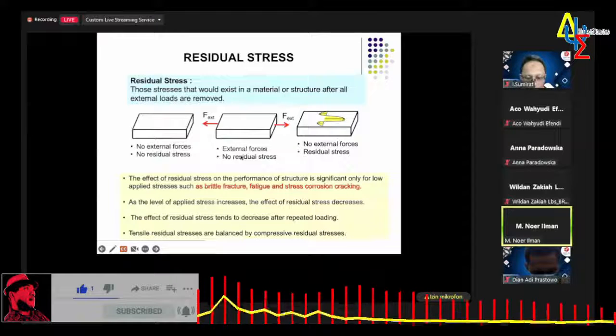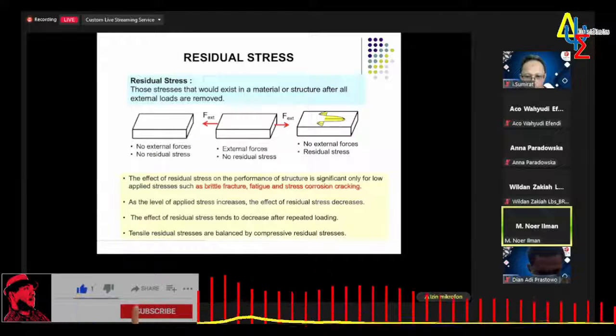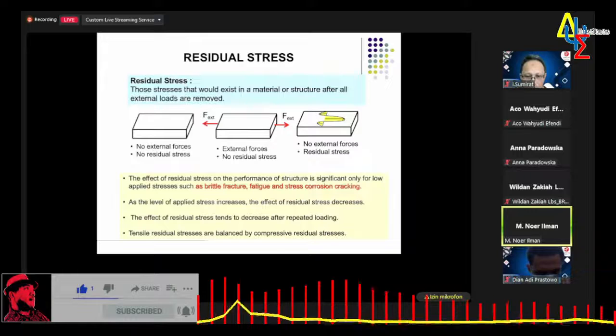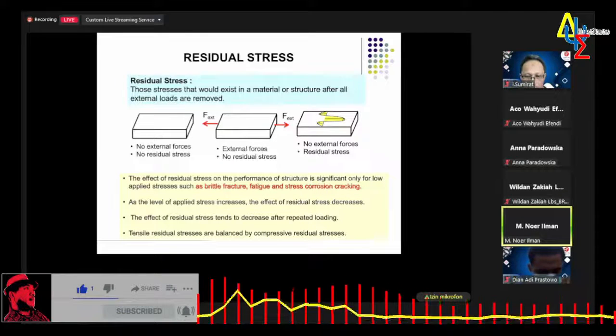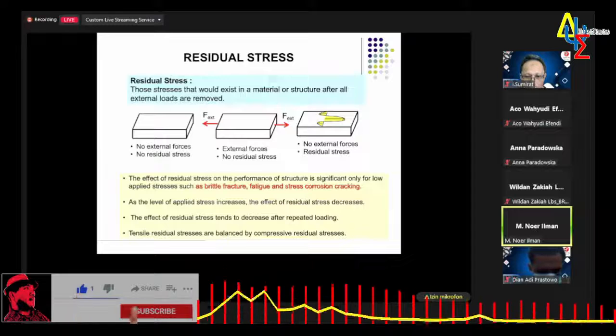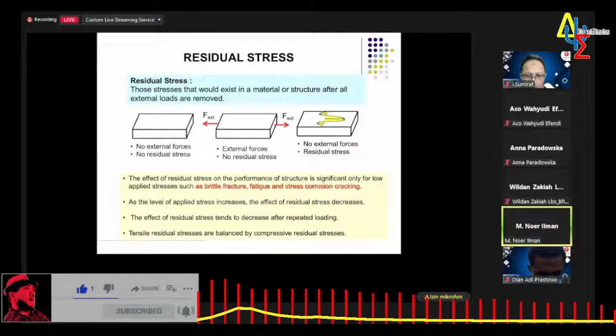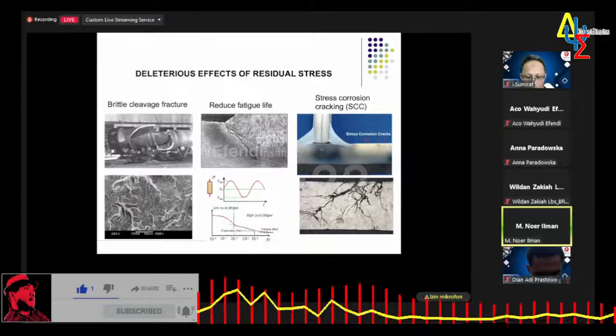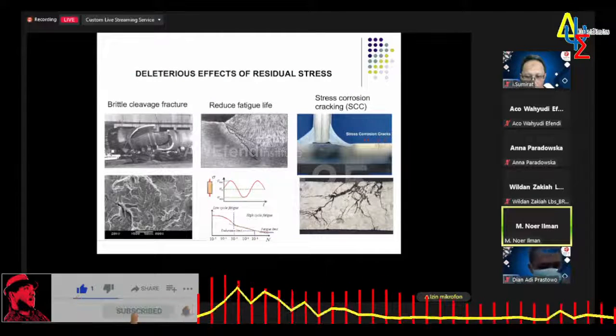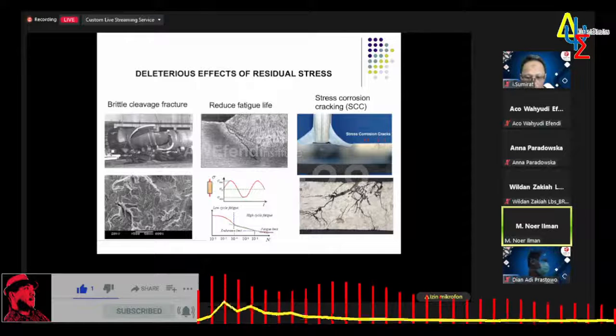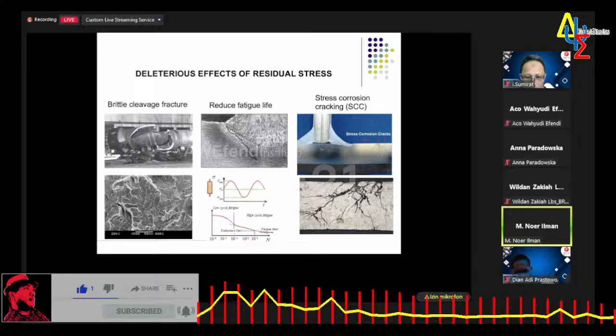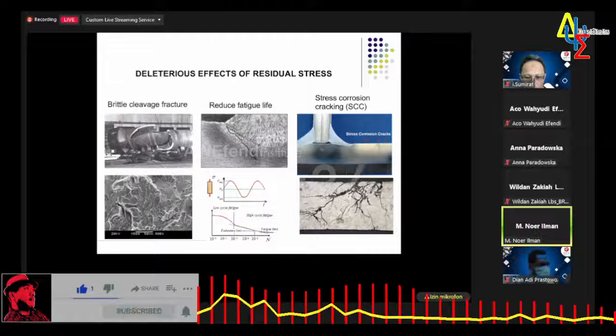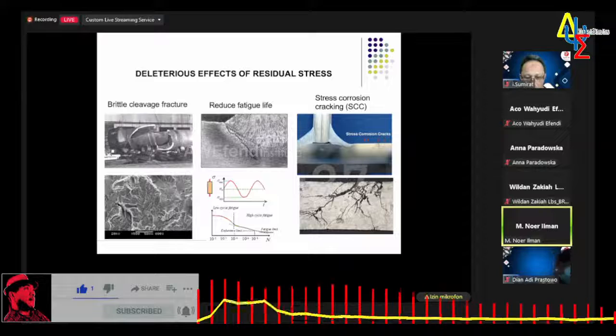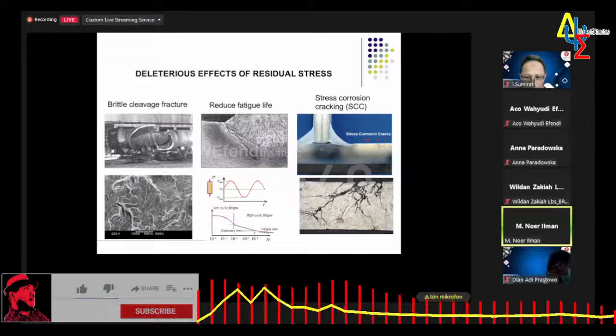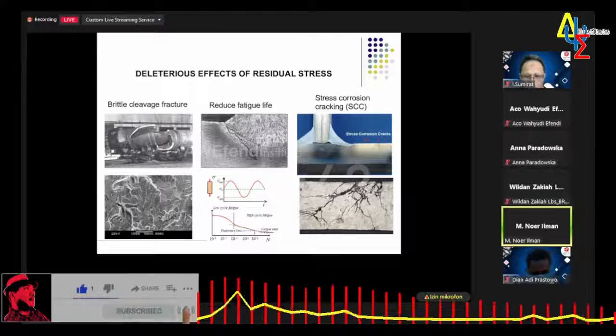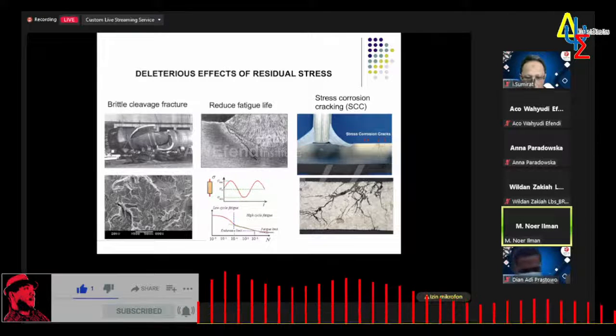Why do we study residual stress? Because residual stress can cause deleterious effects such as brittle fracture, fatigue, and stress corrosion cracking. If we move on to the next page, these are examples of failure caused by the presence of residual stress in welded joints, like brittle cleavage fracture, and then due to the residual stress, the fatigue life is reduced, and residual stress also promotes stress corrosion cracking.